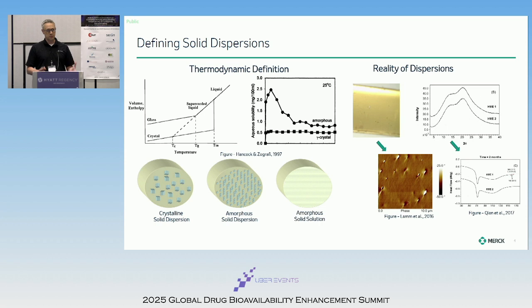And we break it down into three general categories of material. We have a crystalline solid dispersion. Oftentimes we're seeing these types of materials being leveraged for controlled release applications, either oral tablets or long-acting implant type systems. We then have this nebulous gray area of an amorphous dispersion or an amorphous solid solution. But in general, what we're looking for is an attempt to leverage molecular level dispersion of the active ingredient within the carrier system. The reality of dispersions is that there's probably an element of scale of scrutiny here, right? Depending on how closely you look, you can find some degree of heterogeneity potentially in that dispersion. And we've seen that play out not just with the active ingredient, but also with the excipients.